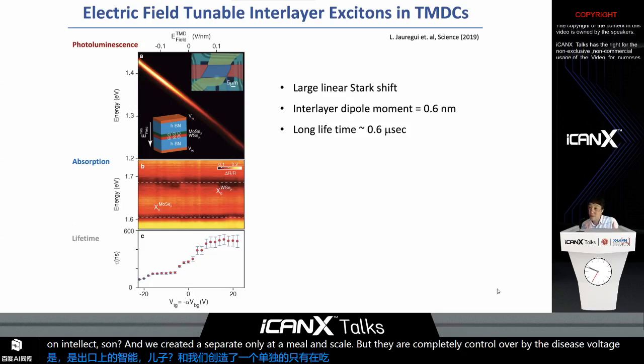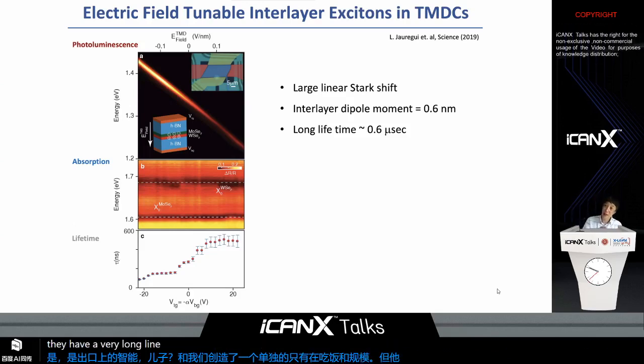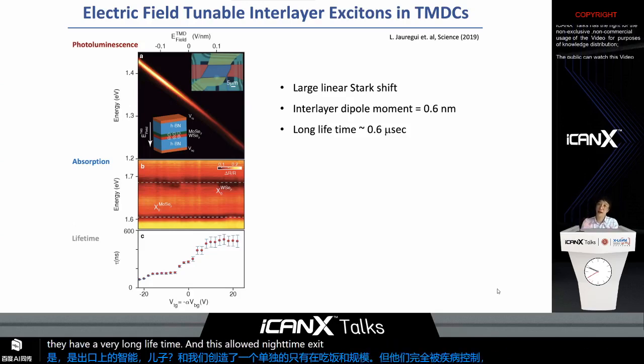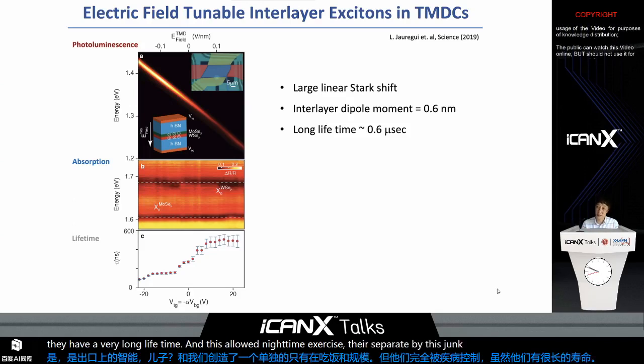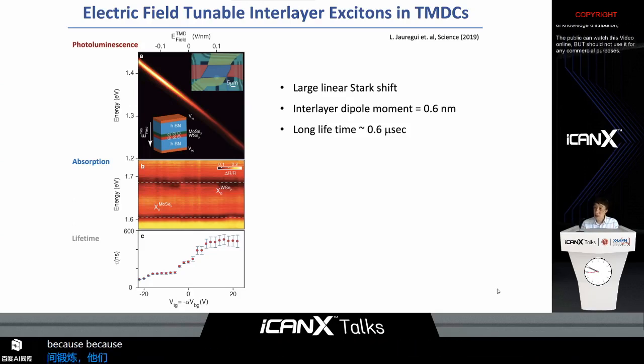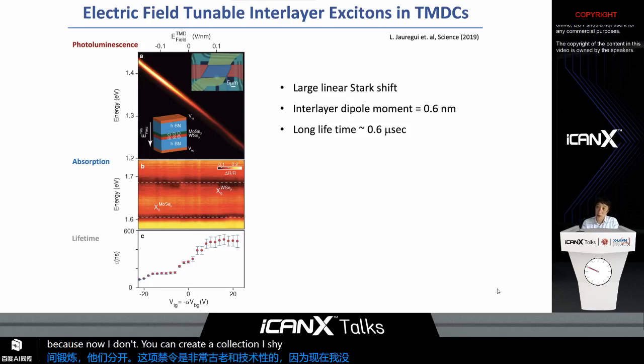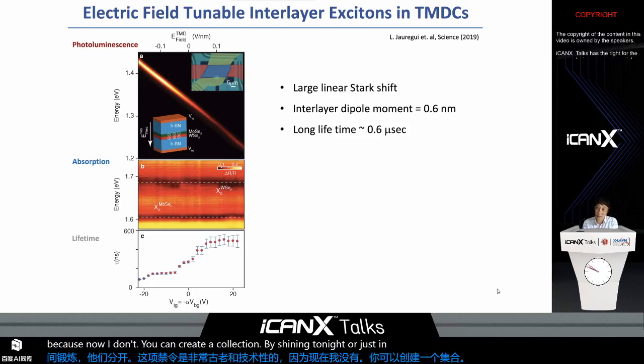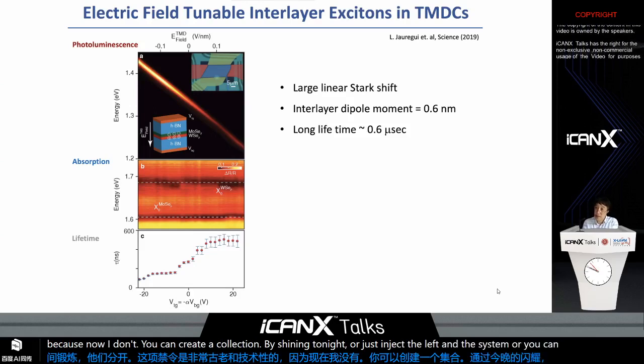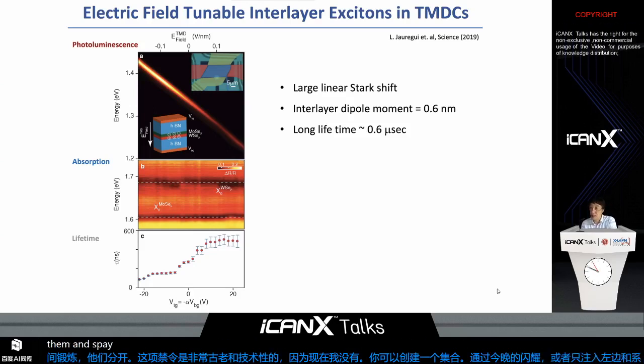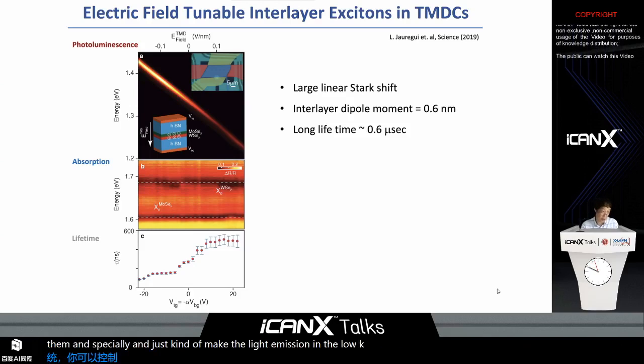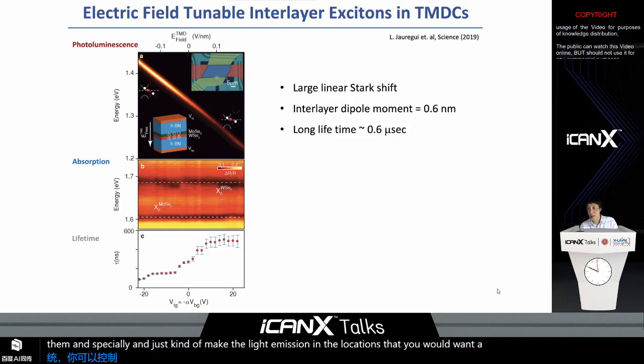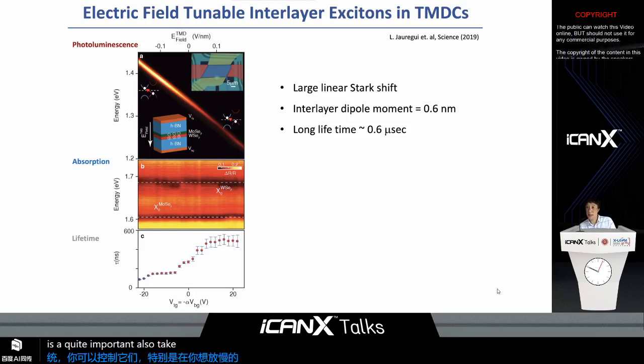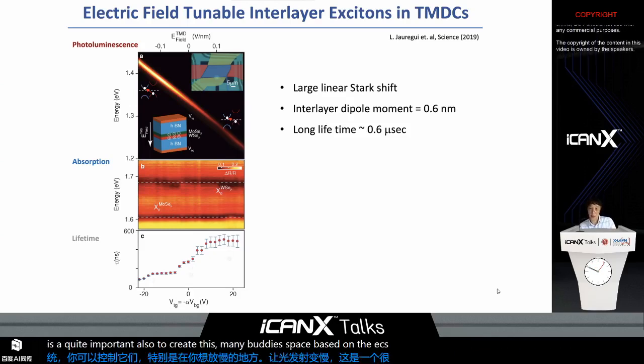But they also have a very long lifetime. And this long-lifetime exciton, separated by this thin junction, is very important technologically, because now not only can you create interlayer excitons by shining light or injecting electrons and holes into the system, you can actually control them spatially and make the light emission at the locations you want. This long-lived exciton is quite important. Also, they create many-body states based on the excitons, which I'm going to cover in a moment.